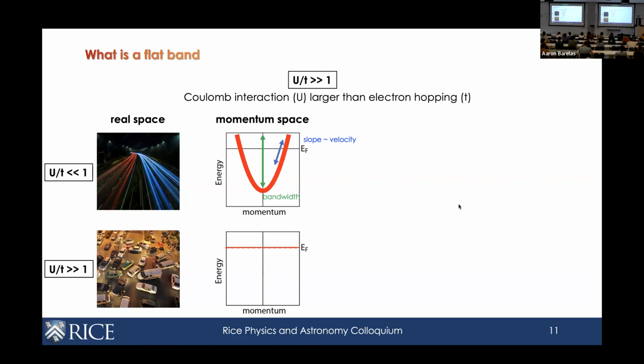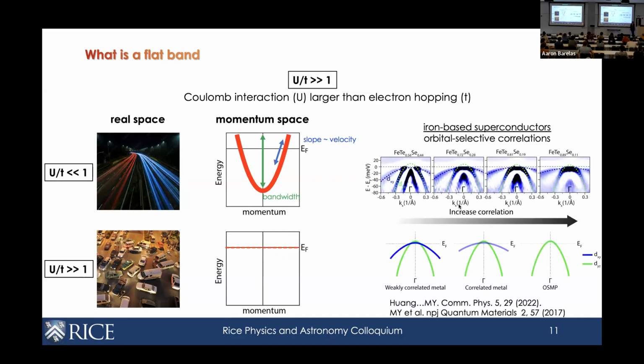Do we actually see this kind of thing in real materials? And we do. This is an example of a material we really like, and I grew up with it as a graduate student. It's one of these iron-based superconductors. What we found is that in this compound, if you focus your eye on this band, this curvy thing, and you dope the system with a certain element, from one end to the other, you can see this band start to get flattened as you go in this direction.